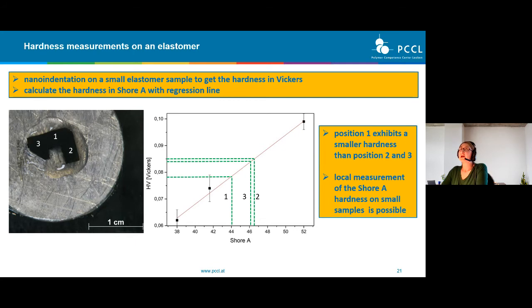And then we did nanoindentation on the small elastomer sample to get the hardness in Vickers, and we calculated the hardness in Shore A with the previously done regression line. What you can see here for this example is that position 1 exhibits smaller hardness than position 2 and 3, and we can say that local measurement of the Shore A hardness on a small sample is possible.